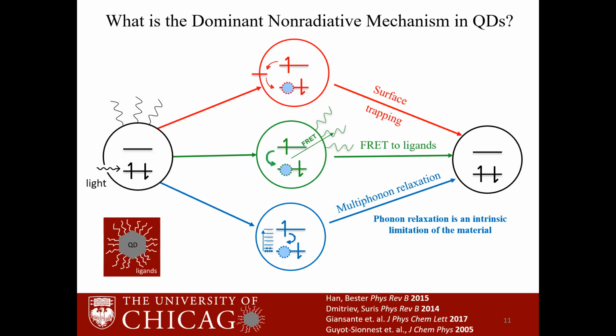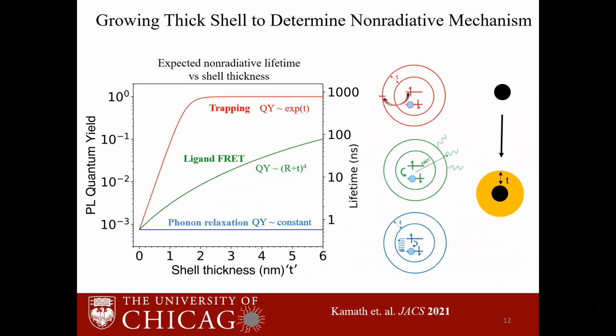You mentioned there's absolutely no effect of the shell, but even if there really is no effect of even a thick shell, I would assume the picture will somehow show some signal of the strain affecting the rate. Okay, you have a good point. So it's a simplistic argument. It depends on what phonon modes are involved. If it is the bulk phonon modes, then yes, the strain can change the phonon frequency and it will change the rate. But also, if the phonons that are involved are the surface phonon modes, then there can be an effect.